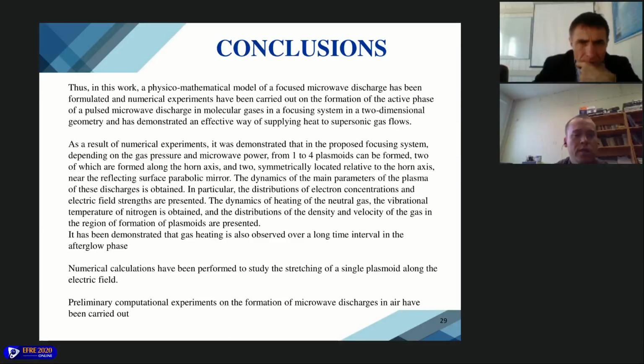As a result of numerical experiments, it was demonstrated that in the proposed focusing system, depending on the gas pressure and microwave power, from 1 to 4 plasmoids can be formed, two of which are formed along the horn axis, and two symmetrically located relative to the horn axis. The dynamics of the main parameters of the plasma of this discharge were obtained. The dynamics of heating of the gas and the vibrational temperature of nitrogen were obtained. It has been demonstrated that gas heating is also observed over a long time interval in the afterglow phase.